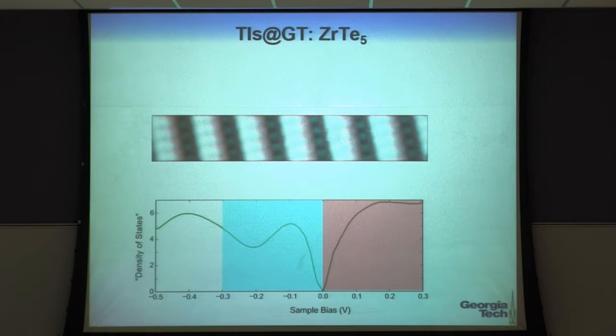Now, I have not taken the time to show things quite as fancy as previously, but what we try to find out is where are the empty states and where are the filled states on the sample. So if I look at the blue areas, those are the filled states, that is, states below the Fermi energy, and I'm tunneling at a bias out here, so I'm sensitive to all those filled states. If I tunnel at a bias out here, I'm sensitive to all these empty states in the current flow, and where both of them overlap is where it's white. Okay, so I color red for the empty and cyan for the filled states, and the overlap is white.